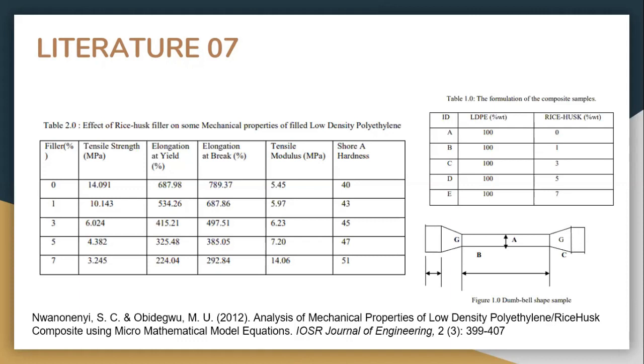In contrast with the study of Atwania, Nwanonenyi and Obidiegwu concluded that with the addition of rice husk fillers, there was a decrease in tensile strength of the polyethylene. However, both of their research showed the direct proportion of tensile modulus and hardness to the addition of rice husk fillers. Nwanonenyi and Obidiegwu also concluded that these fabricated composites can be used in domestic products and electrical housing units, where the level of water absorption and low strength of LDPE is not a critical factor. According to them, the addition of the rice husk fillers can also help reduce the material cost since wastes were used.